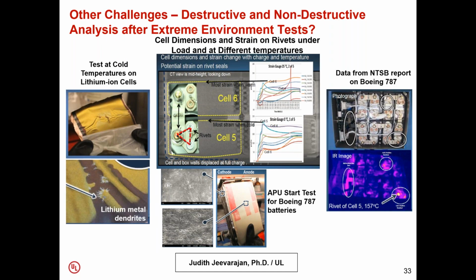Some of the other challenges with temperatures are that when we have cells like in the Boeing 787, where we had rivets that the terminals were attached to, we noticed that depending on the temperatures, the rivets on different cells had a strain. And we also noticed that when you have high currents going in or out of the cell, the electrodes that are attached to the terminals can get pretty hot inside the cell. And the current collector getting hot can also melt the separator in certain portions of the cell.